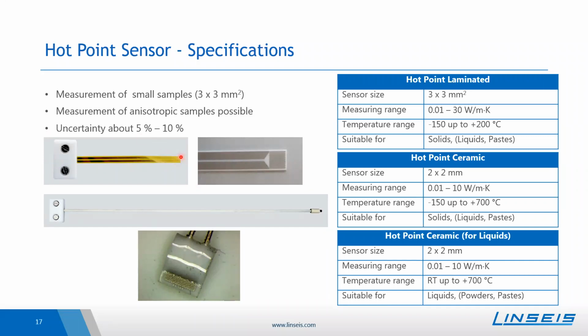Here you see again the pictures of the different sensors, so the Kapton foil-based version, the ceramic one for the solids, and here this long rod with the tip especially suited for liquids. Here you see an image taken by a microscope of this tip, where you see the wires on the complete front. The hot point sensor can measure also low conductive materials up to materials with a thermal conductivity of 30 watt per meter Kelvin.